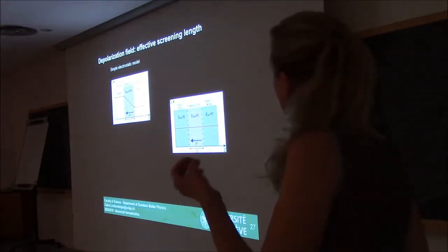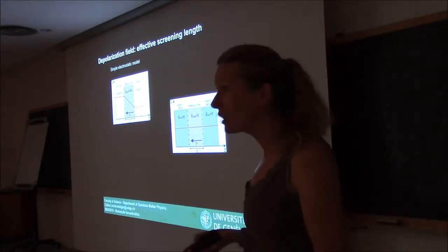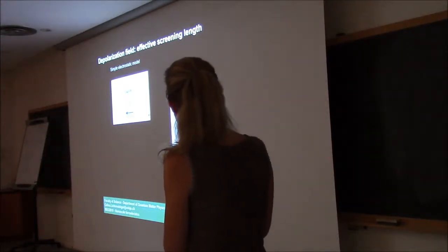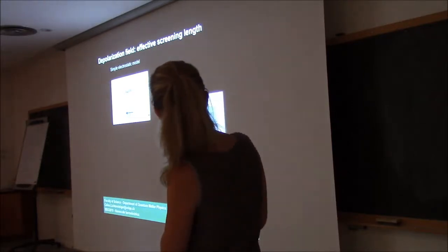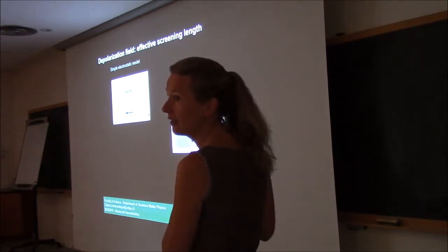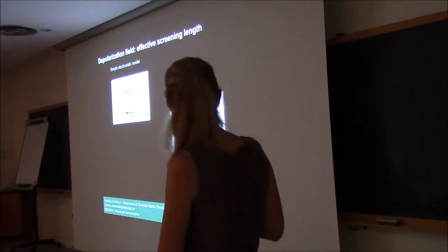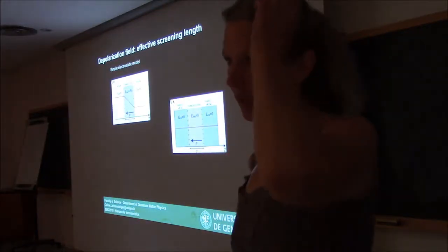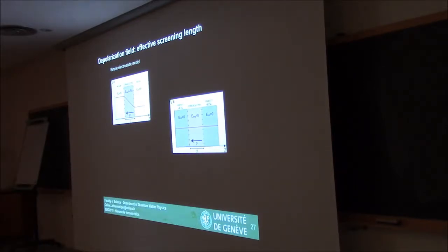Now, we said that if we put some electrodes, perfect metals, you can screen these surface charges. So if you do that, here you have a perfect metal, a perfect metal. These two perfect metals will completely compensate the surface charges here and here from the polarization. And now everybody is happy because this screening will compensate exactly the field inside the material. So you will have a zero depolarization field, and so the polarization is stable. Except that in reality you cannot achieve absolutely perfect screening. So how can we model that?